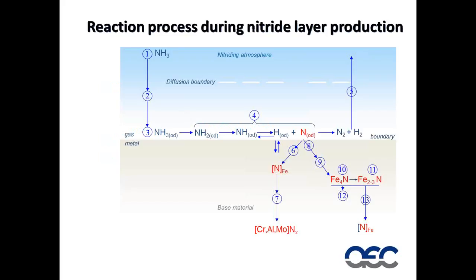Please don't get put off by this. It's not as complicated as it looks. The first part here in the red circle says that all we're doing is we're taking ammonia, which is in the general nitriding atmosphere, and it diffuses naturally in air, so there is some ammonia in contact with the steel surface. The next part is the reduction of that ammonia. That's a chemical reaction which turns ammonia, which is nitrogen and hydrogen. Basically, at the correct temperature and the correct conditions, it creates atomic nitrogen and atomic hydrogen.